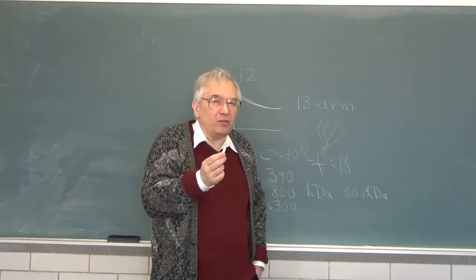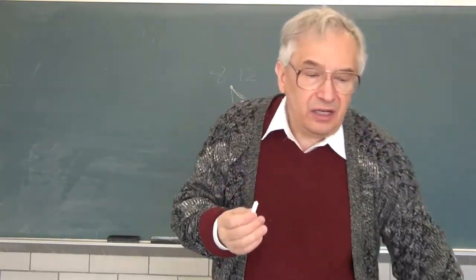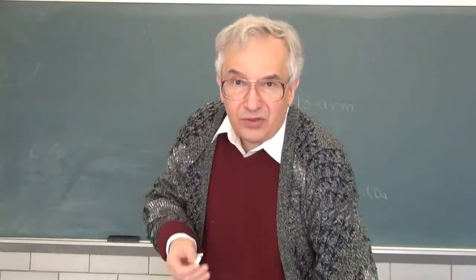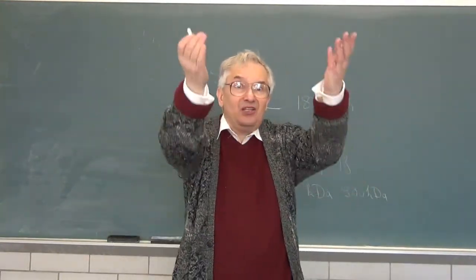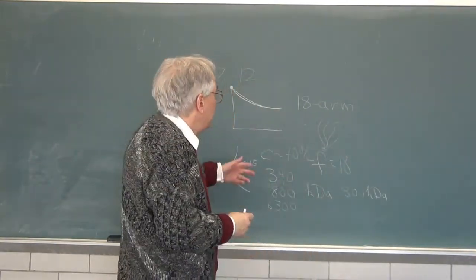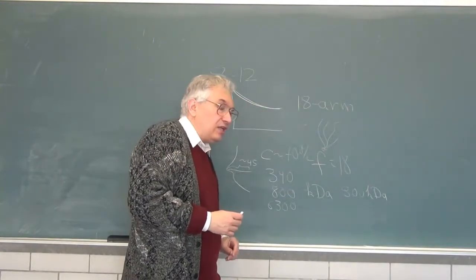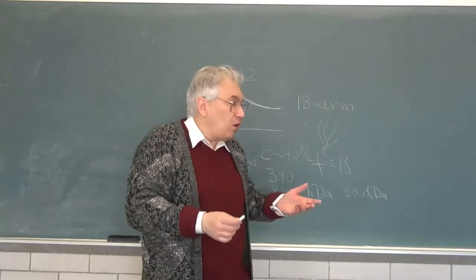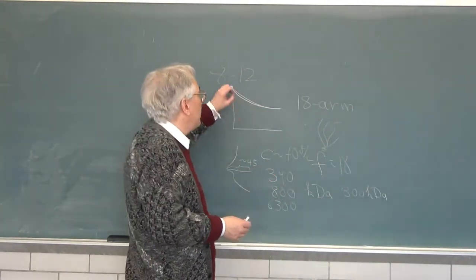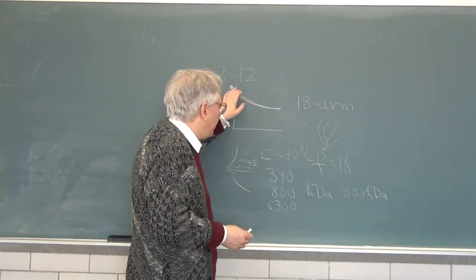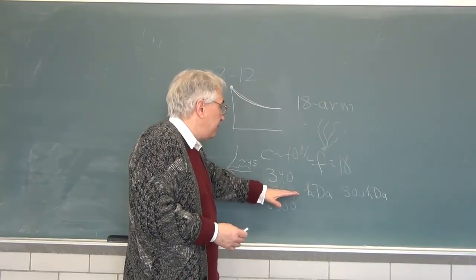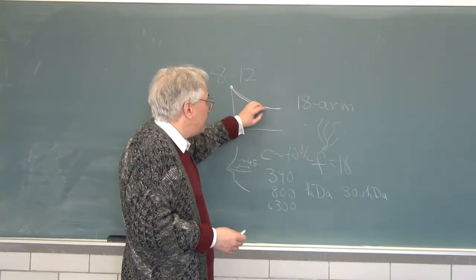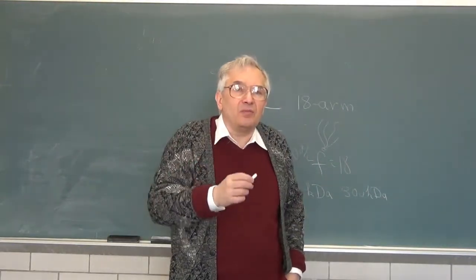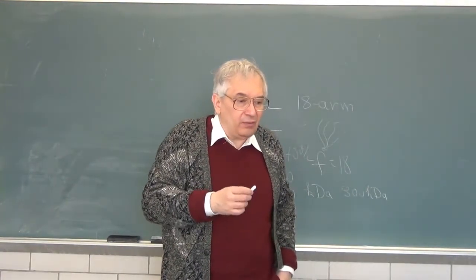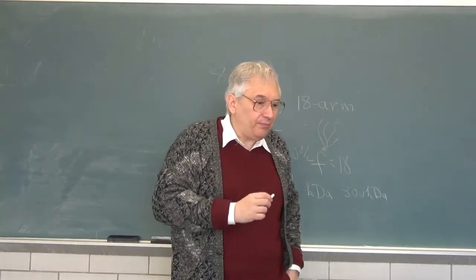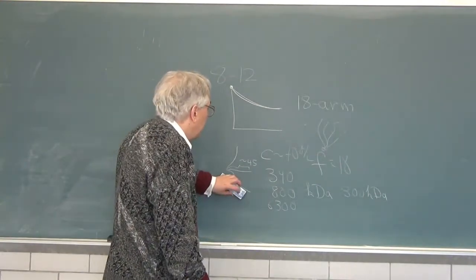Why is this result significant? Why should we care that we can measure a linear chain and a star chain that start out the same size, and then we find that as we run up the concentration, the diffusion coefficients track? And the answer is that if you believed that star chains and linear chains diffused through completely different processes, there'd be no reason to suppose the two curves would track each other. Clearly, you can always find some linear chain of some molecular weight whose diffusion coefficient matches the diffusion coefficient of the star chain. But there's no reason for the two curves to lie on top of each other if you happen to believe they use completely different diffusive mechanisms. Well, rather clearly, that's not what we are seeing. We see one curve.